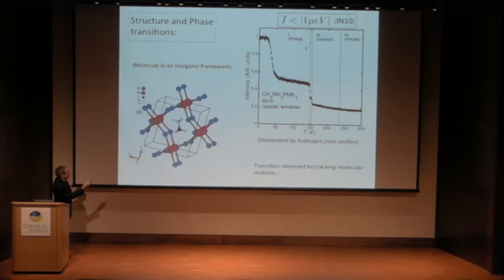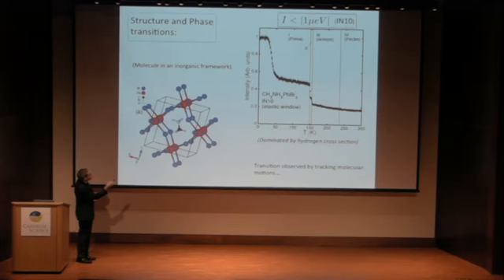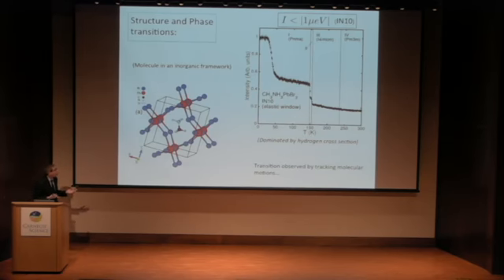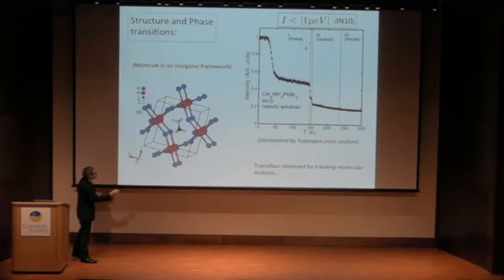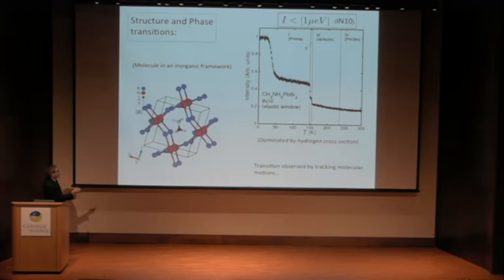Basically, I'm integrating over all detectors and plotting the intensity as a function of temperature. What this is sensitive to is any dynamics that enter into the resolution of the spectrometer, which is about 1 microeV in this case. Now, because hydrogen has such a huge cross-section, when you integrate across all detectors, you're really sensitive to just the molecular motions in this system, dominated over all these other elements. So what this is telling you is that at low temperatures, as you heat up, there's something moving outside the time window of the spectrometer.